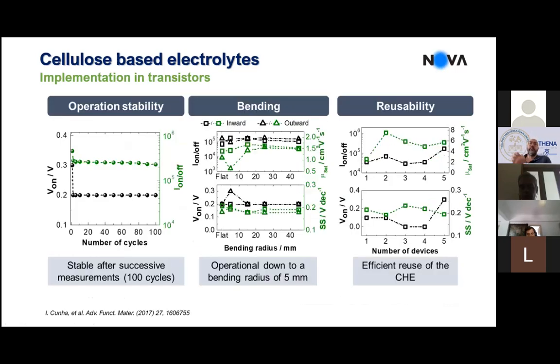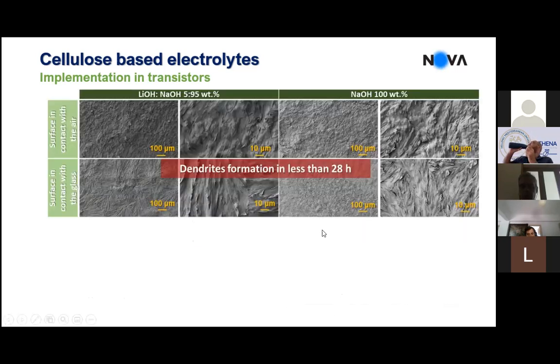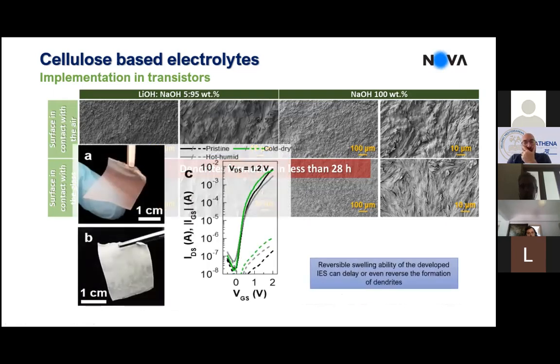based electrolytes, and I will skip this slide, when you dissolve the cellulose in sodium hydroxide, is that then you have the tendency to have dendrites formation after some time in these membranes. That you can recover if you expose them to humidity, but it's not the best way to do it, of course. But nevertheless, this is just to show that the performance of the transistors can be recovered after we expose these membranes to a humid environment to get rid of these dendrites. But the best thing, of course, is to tune the composition in order to avoid the formation of these dendrites.